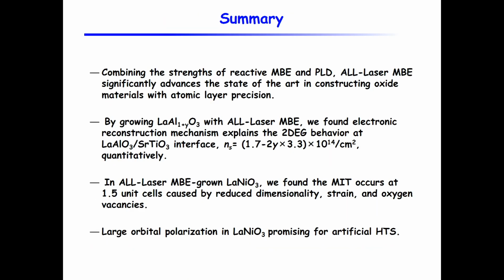So to summarize, I told you that we combine the strengths of MBE and PLD to develop this atomic layer by laser MBE, and we believe that allows us to push the thermodynamic boundaries to grow materials further, and advances the state of the art in growing these oxide materials. I showed you the result of lanthanum aluminate on strontium titanate, and because we were able to grow layer by layer at this high oxygen pressure, we could suppress the oxygen vacancy effect, and we show that the behavior of the carrier density is consistent with the electronic reconstruction mechanism.